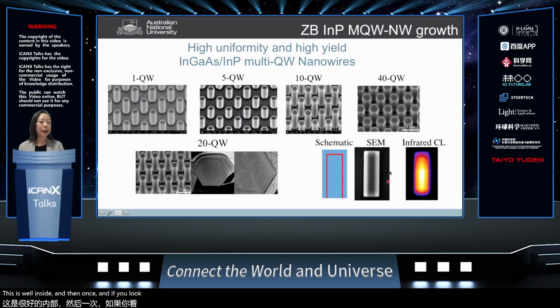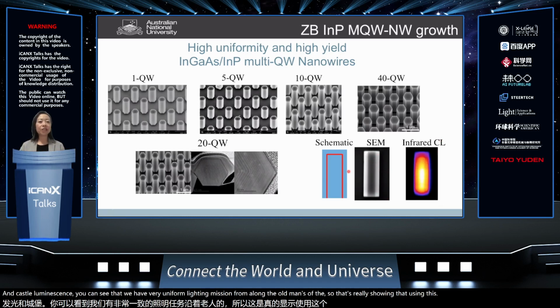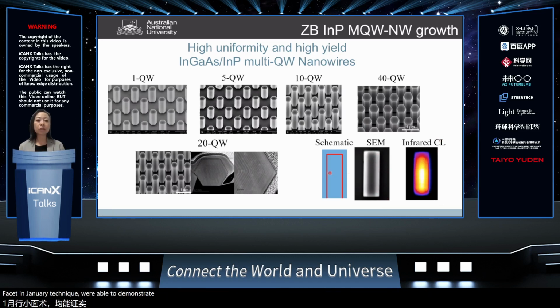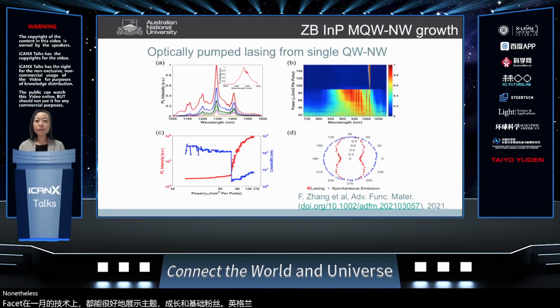And if you look at the cathodoluminescence, you can see that we have very uniform light emission along the whole length of the nanowire. So that's really showing that using this facet engineering technique, we're able to demonstrate multi-quantum well growth based on zinc blende nanowire. And of course, we want to see whether the optical quality is good. From one single nanowire device, we show that by doing optical pumping, we also can have good light emission from our quantum well. So the 1.3 micron definitely is coming from the quantum well, not indium phosphide.